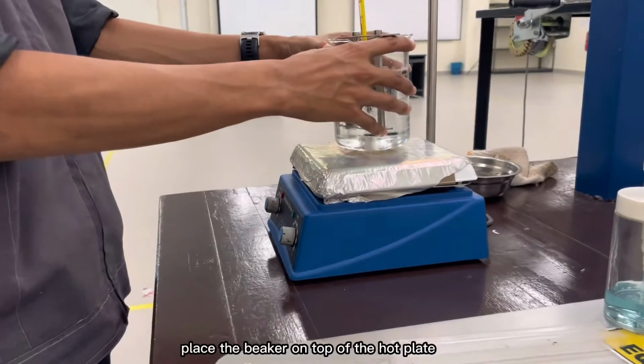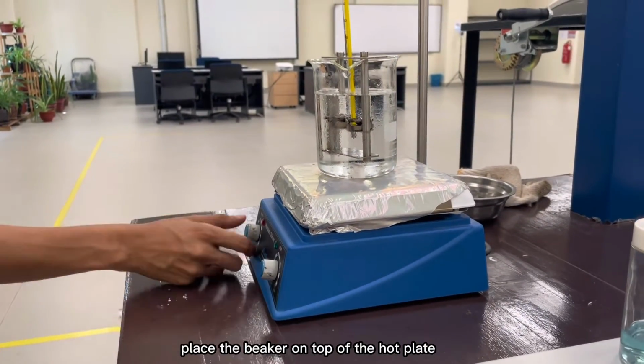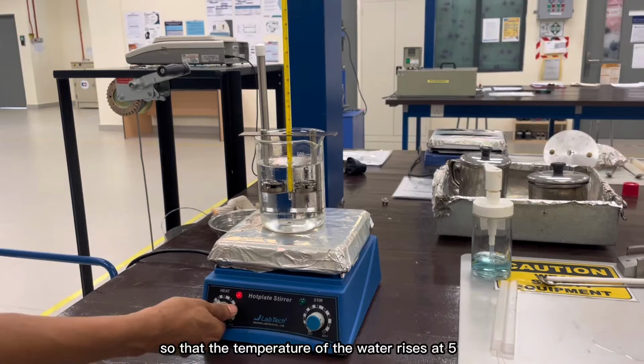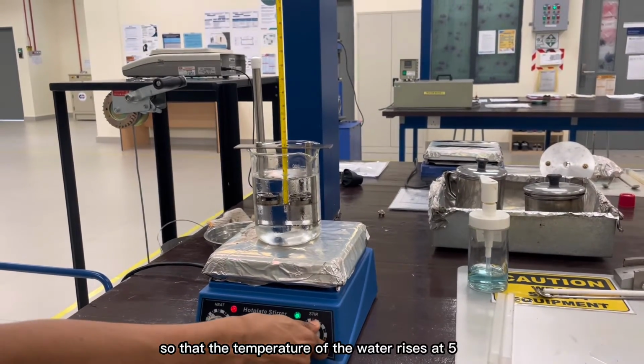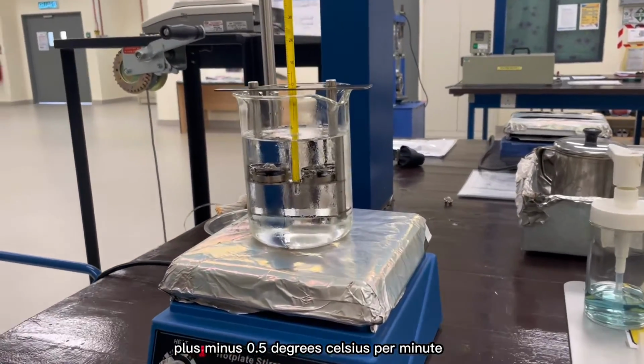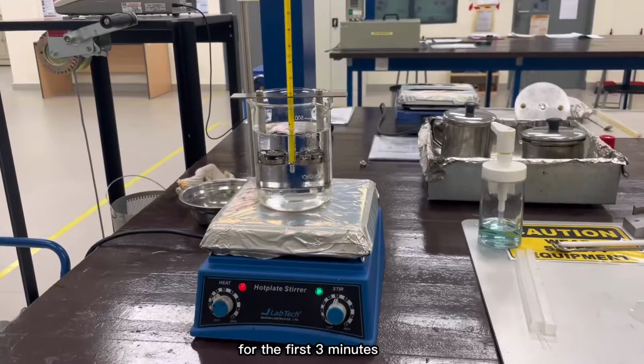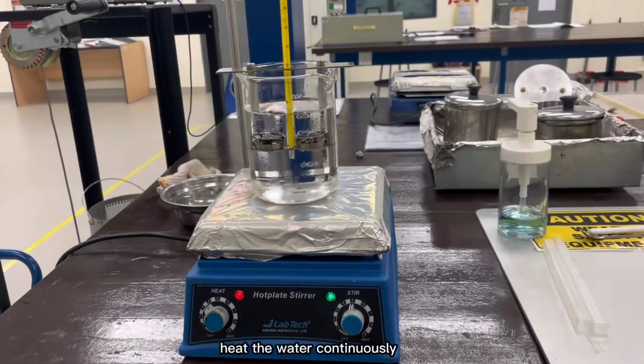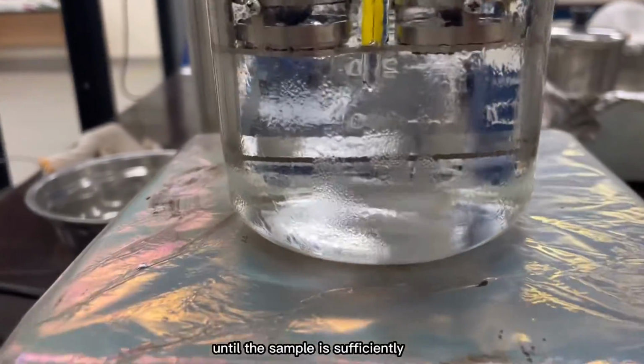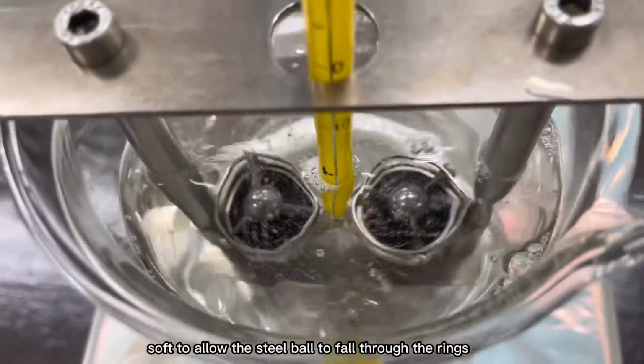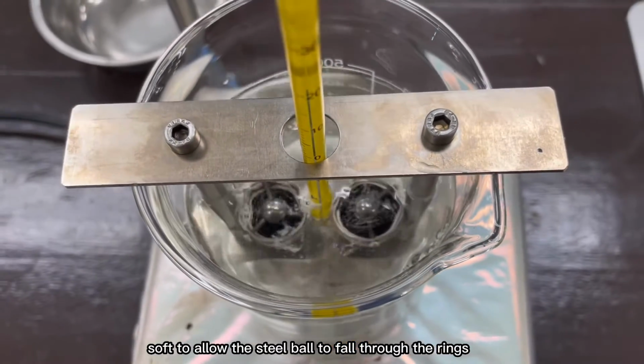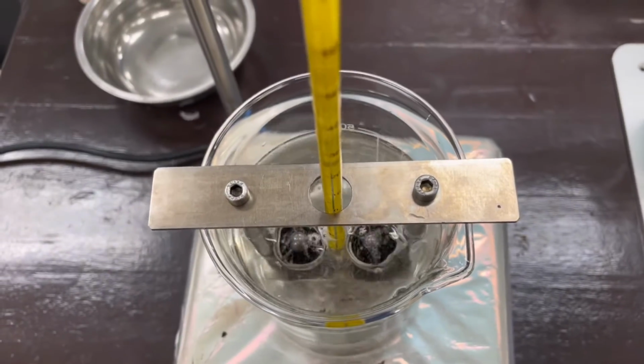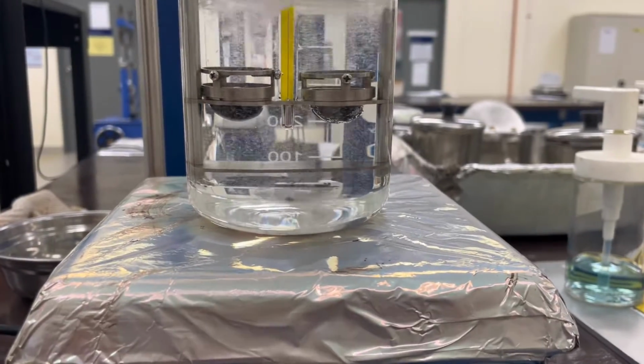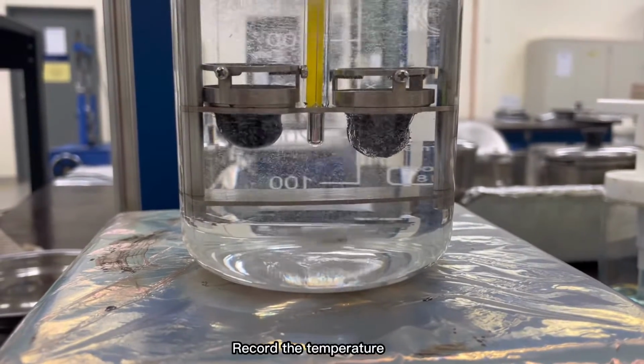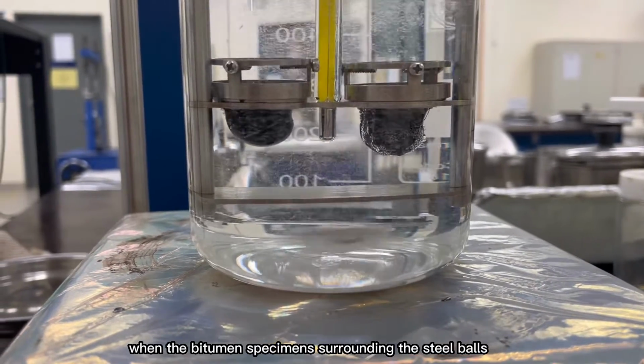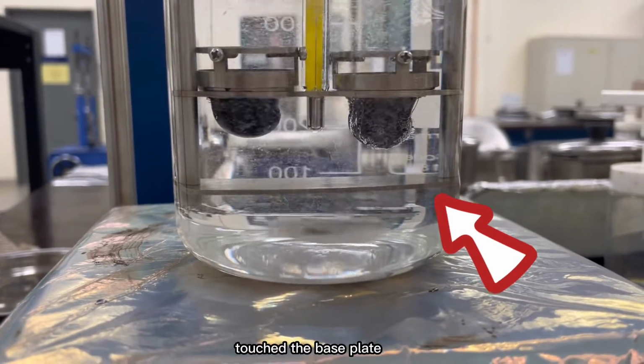After 15 minutes, place the beaker on top of the hot plate. Heat the water so that the temperature of the water rises at 5 plus minus 0.5 degrees C per minute for the first 3 minutes. Heat the water continuously until the sample is sufficiently soft to allow the steel ball to fall through the rings. Record the temperature when the bitumen specimen surrounding the steel balls touches the base plate.